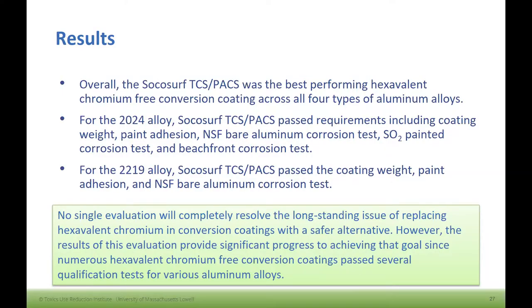For the results of the testing, overall, across all four aluminum alloys that we used, the Socosurf product was the best performing hex chrome free. And specifically for the more challenging alloys with the higher copper content, the 2024 Socosurf passed the coating weight, the paint adhesion, the NSF bare aluminum, the SO2 test, and beachfront corrosion test. So it passed a number of the tests. So that was great results.